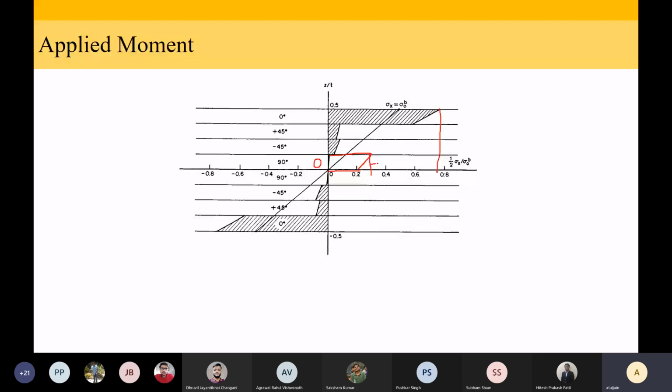So it is the same idea, because our assumptions are similar. It is giving us similar results as the Euler-Bernoulli bending equation, that the layers at the top and bottom are getting more stress. There it was due to the fact that I was being increased, and here it is due to the fact that we are making similar assumptions, but the A, B, and D matrix is changing depending on how we lay up the sequence, how we lay up the laminas.